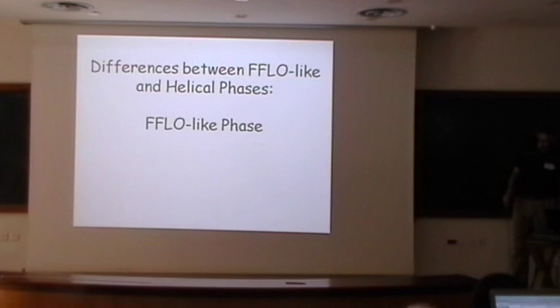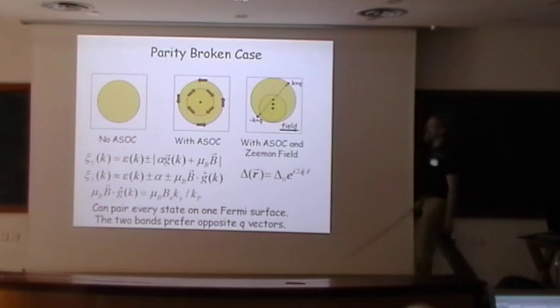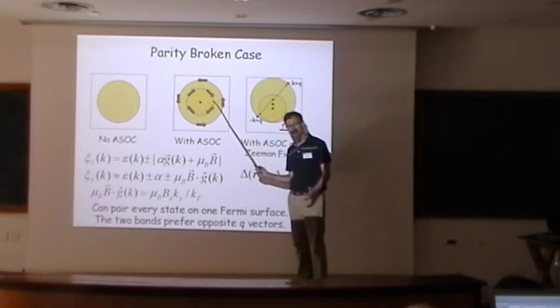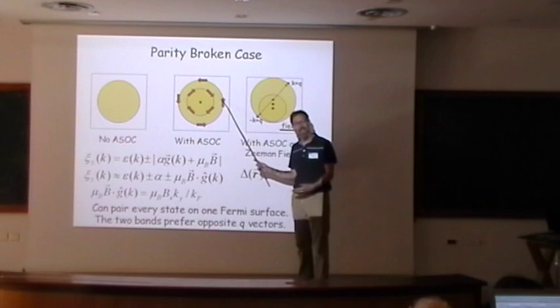I'll tell you why. By making the spin-orbit coupling vanish here, I can make a usual spin singlet superconductor from exactly this language. There's no reason for me not to choose this particular spin basis at every point in k. Then I can introduce a gap in this chirality basis. I can solve the problem because we have complete spin degeneracy in the limit that there's no spin-orbit coupling.